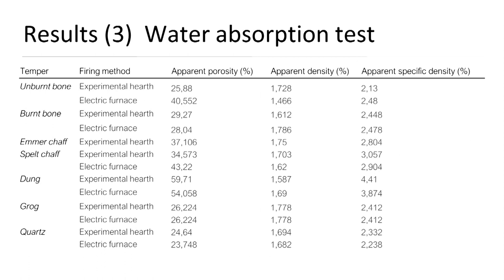In the same line, in the water absorption test, the same group, grog, bone, and quartz, had lower porosity, while the other had a higher degree of porosity. Again, more consistency was observed in hearth-fired specimens.